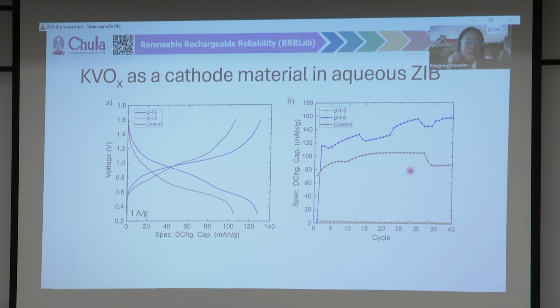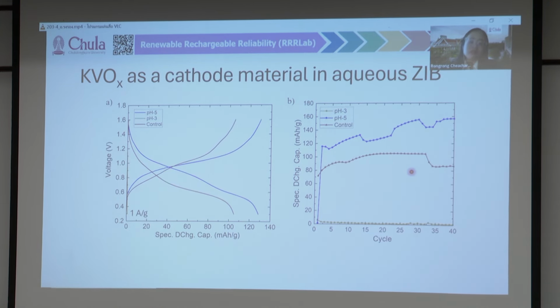So as expected, when we go further into the battery, actually the control one didn't work at all. This phase didn't work well as a battery, but the cathode material that we synthesized at pH 3 and 5 seems to work as a battery. For this one we did the galvanostatic charge discharge at a current rate of 1 amp per gram, and it gave us a good capacity above 100 milliamp hour per gram for both cases. But the one synthesized at a pH closer to neutral, like pH 5, seems to be better in terms of both performance and stability when we look at this graph B.